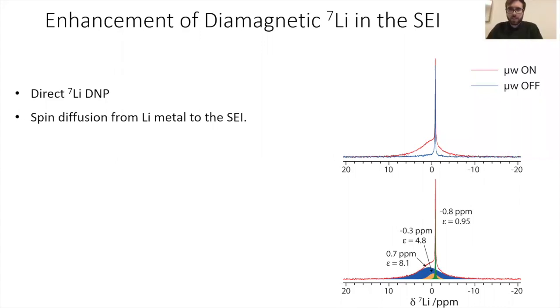Okay, so then the next question on our list is, could you identify all the heterostructures, the interface of the lithium and SEI? So we can certainly identify, I would say, all the different chemical species. The actual structure is not really something that we're sensitive to. We're sensitive to the distance from the lithium metal, but knowing whether that's porous or dense or structured in any way is not something I think that we're really sensitive to. You have to wait for lithium metal MRI, which I don't know if that is possible. That's just something off the top of my head. So I don't think that we're sensitive to that detail.